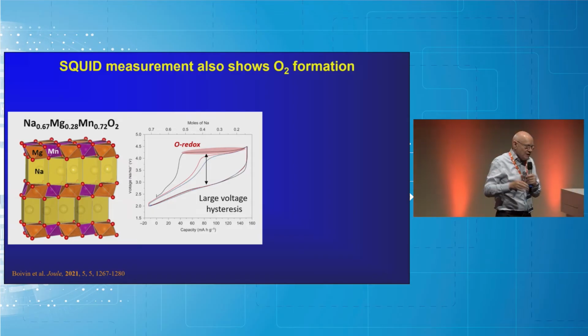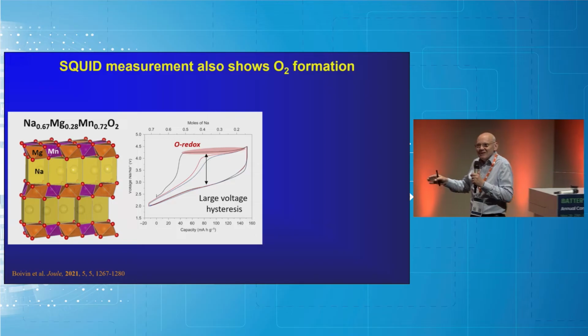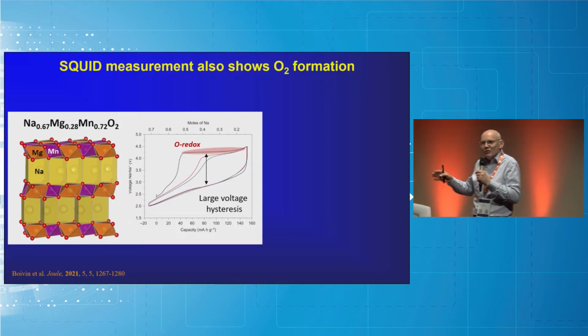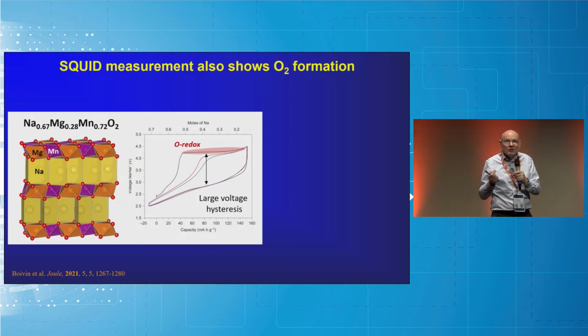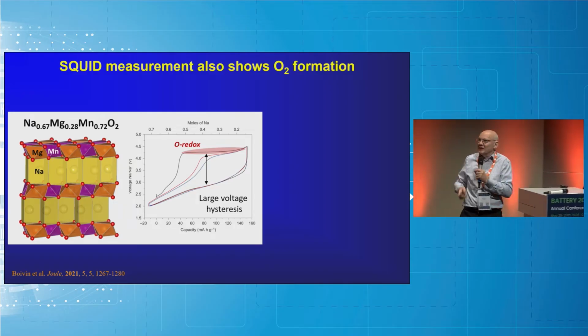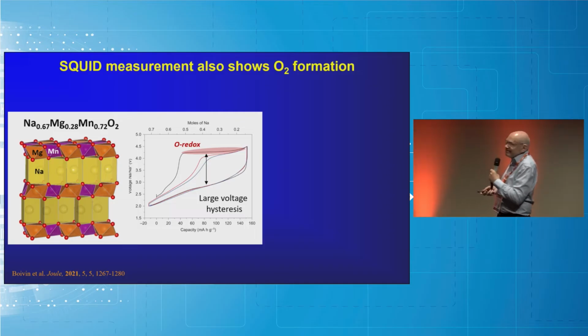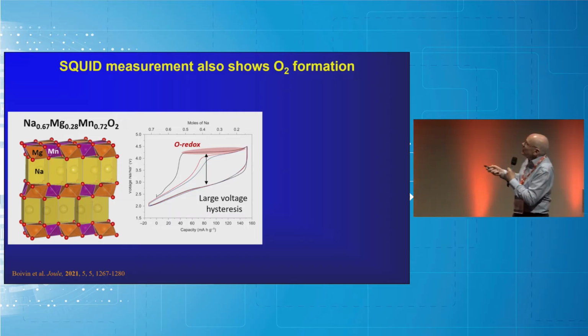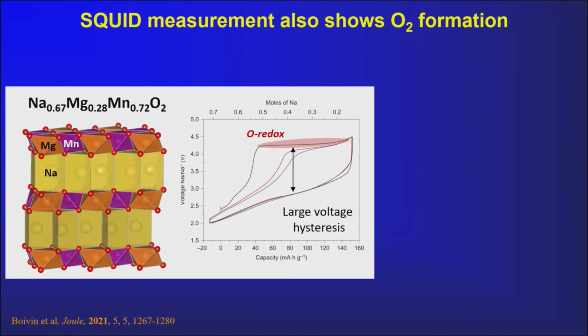So we wanted to suppress that because ultimately you don't actually want O2. I'm going to talk quite a lot about it, but ultimately, as I'll show you, you don't really want to get that. You want to get true oxygen redox, true reversible hole formation on oxide ions. But we're not quite there yet. But we thought we might be able to do that with this material because this is magnesium, no lithium on the transition metal site. So this is sodium in the alkali metal layers, magnesium and manganese on the transition metal layers. And we thought magnesium might stay where it is, unlike lithium. No vacancies, no formation of voids, and therefore you can't have O2. That was the thinking. We were, of course, 100% wrong, as you can see from this load curve.